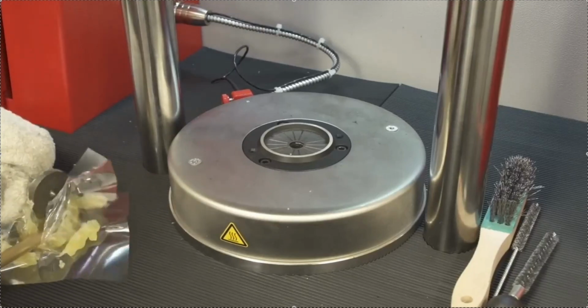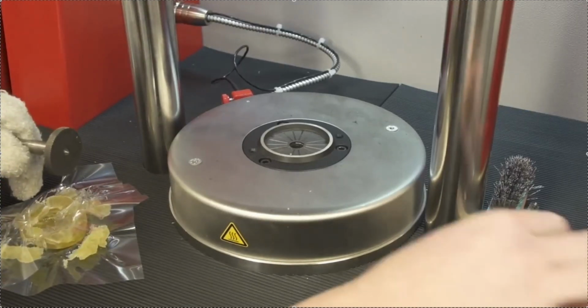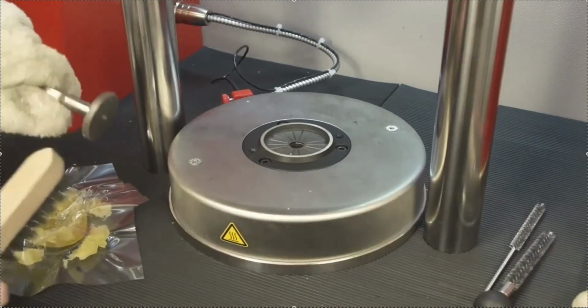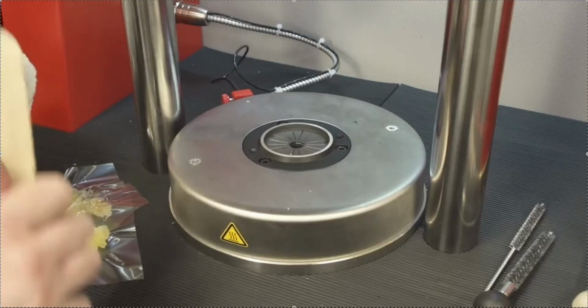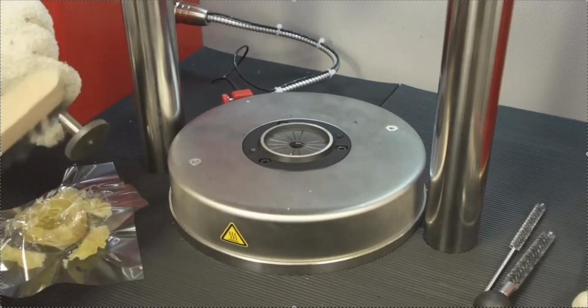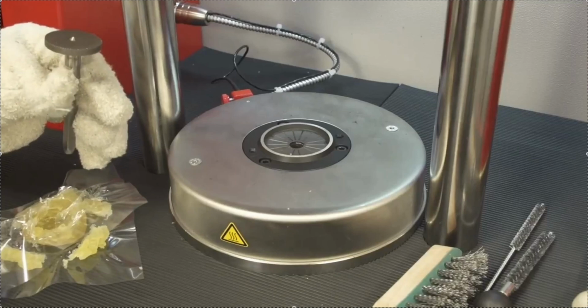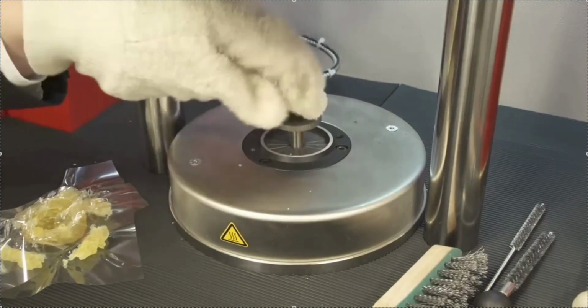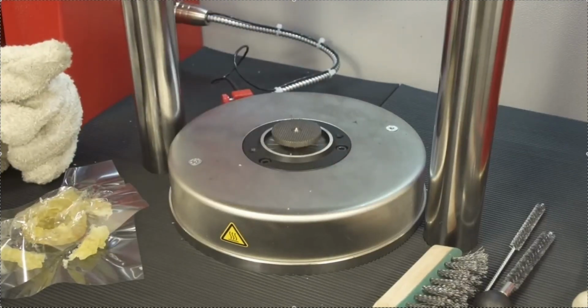Now, if you have ever looked at a rubber test certificate, you've probably seen something like ML 1 plus 4 at 100 degrees C. This is the standard way viscosity is measured using the Mooney Viscometer. The M stands for Mooney and the L stands for large rotor, which is typically used in standard tests. The 1 plus 4 means the test takes place over a total of 5 minutes.